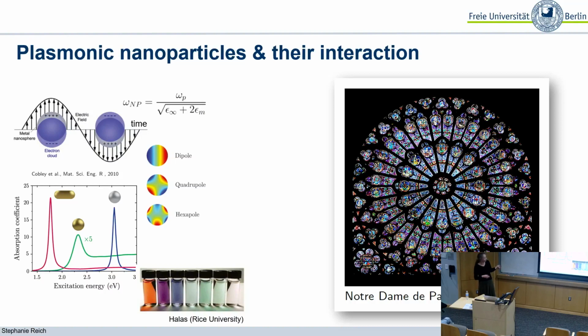You can also change the shape. Here's the simplest change: if you make a little rod out of the spherical nanoparticle, then the longitudinal mode that oscillates in this direction will move to smaller energies. And here's a collection from Naomi Halas's group at Rice University, where they produce metal nanoparticles made of different metals and different sizes and shapes, and you can see how beautifully you can shift the colors around.